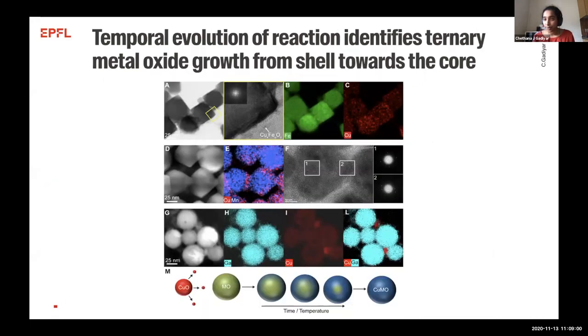The next step that we wanted to do was to understand the reaction intermediates that we are forming during the formation of these materials. So we started annealing the materials for shorter times so that we could look at the intermediates of this reaction. We did it for the case of copper iron oxide, copper manganese oxide, and copper gallium oxide. And in each of these cases, what we saw is that we had a shell of copper-based ternary oxide.